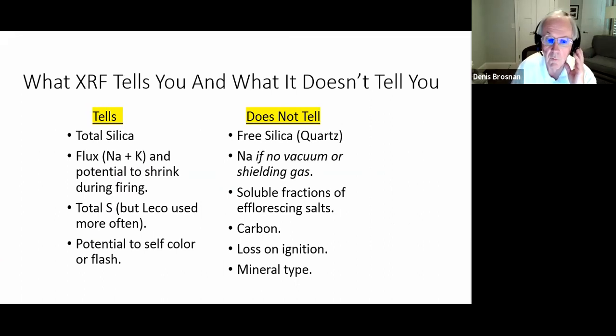So what it tells you and what it doesn't tell you. XRF, X-ray fluorescence, tells us the total silica. It doesn't tell us the free quartz, or the combined quartz. It just tells us the total. It tells us the flux that's present. Particularly, I've highlighted sodium and potassium, and that tells us about the tendency of the ceramic to vitrify or shrink on firing. But it won't tell us the sodium if there's no vacuum or inert gas shielding.